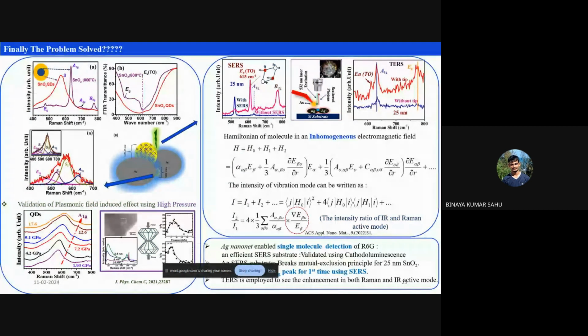And here we can see a very small thing was coming out from this particular spectrum. Okay, so the hidden spectra was finally enhanced using the silver. And this work was also published in ACS Applied Nano Materials. And to cross verify that, again we did some other experiment, that is a high pressure experiment, because as you know,